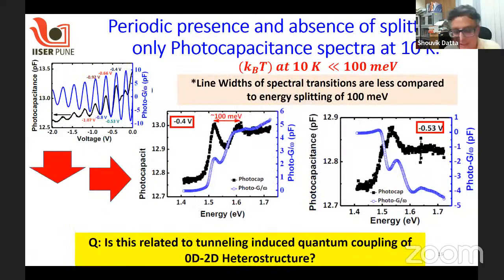A very interesting turn happened when we decided to keep our bias fixed at the maxima and minima of these photocapacitance oscillations, say at minus 0.4 volt, where we see a maximum in both conductance and capacitance, and do spectroscopy. We see in the photocapacitance spectroscopy two very nicely split, distinct resonant-like excitonic features. However, with a bias at minus 0.53 volt, the minimum of those oscillations, it turns out to be a very broad peak, and the well-defined splitting of 100 millivolt between the peaks vanishes.